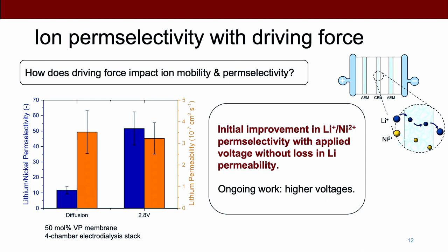So these are diffusion tests with no potential applied. This is electrodialysis, and we've added several other voltages here, driving forces for the transport. But in short, we can preserve the permeability in yellow here, so the flux, more or less, of the ions, but we can increase the selectivity we see for lithium over nickel just by applying electrochemical potential. And this is really exciting to us, because this tells us we can do this in electrodialysis and do it with a selective membrane. So we're combining membranes and processes.